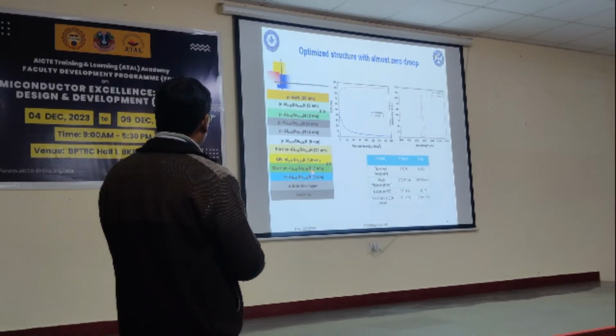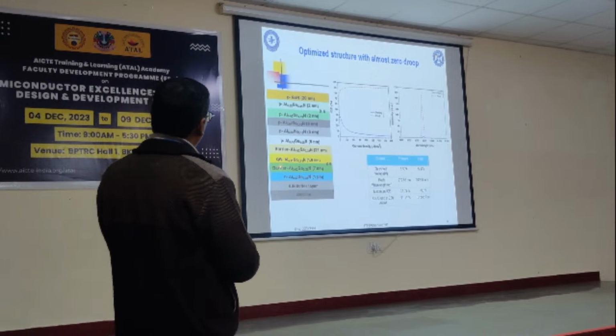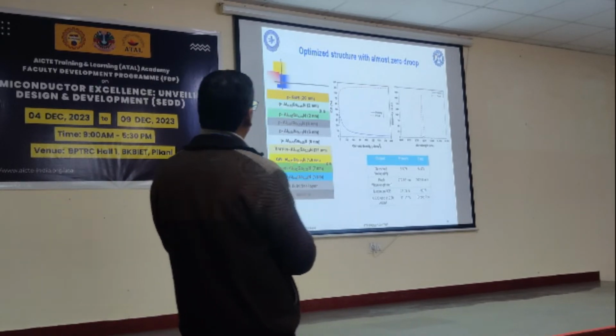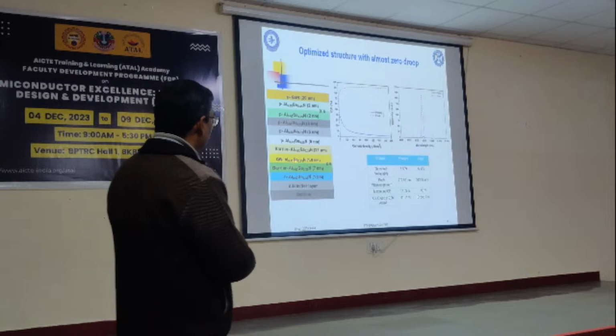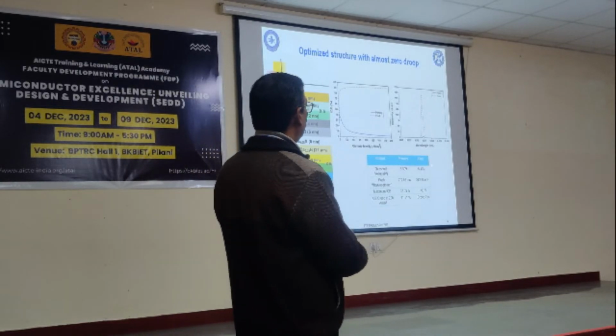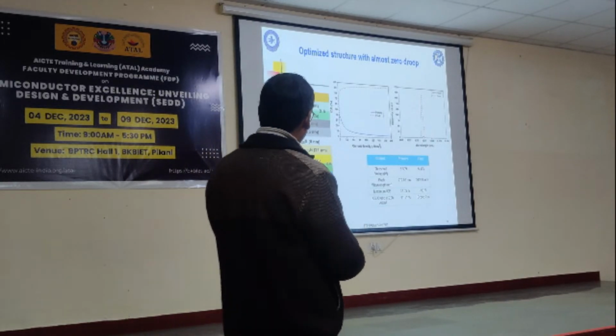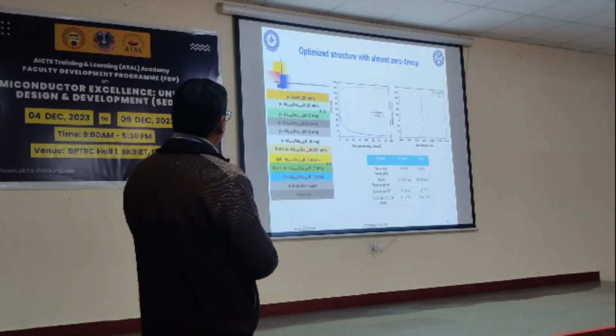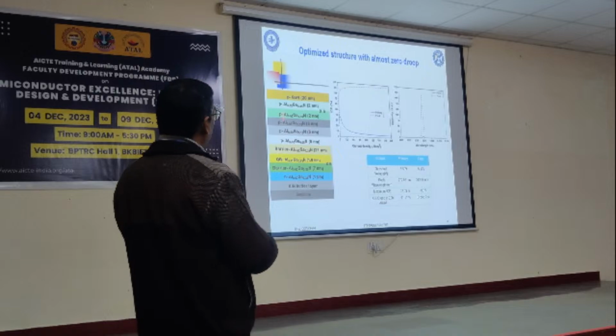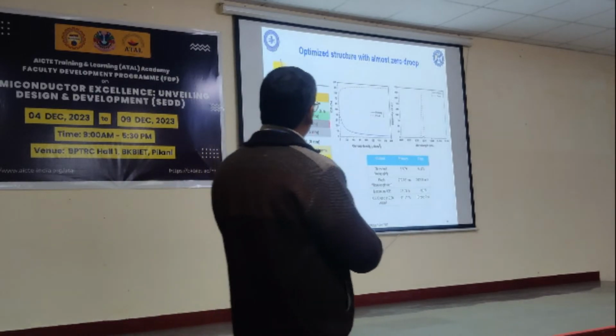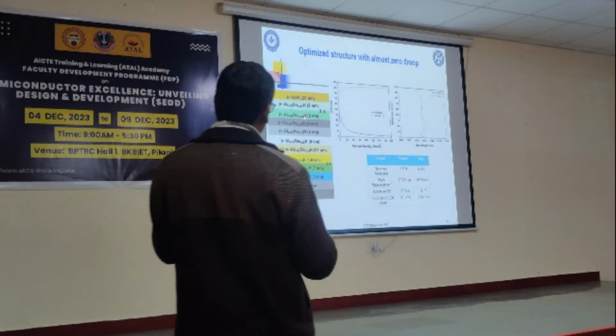So here you see the aluminum composition in the well region is 47%, because that is what we need depending on the emission wavelength, and the barrier is the other, 62%. And in addition to that, there are various superlattice structures and an electron blocking layer we have considered to optimize that droop.